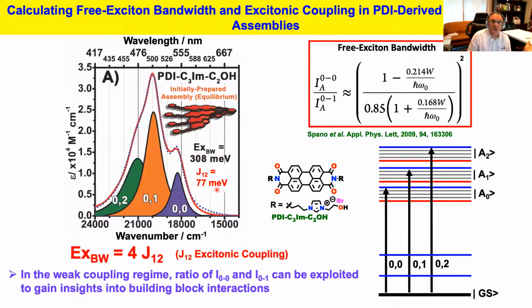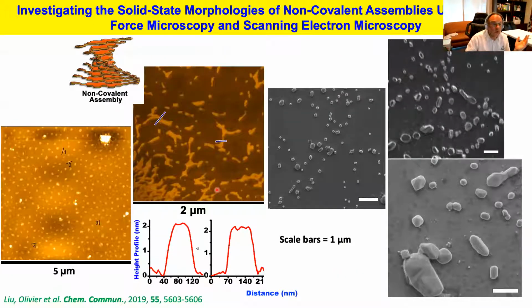Now, of course, I'm talking about solid state deposition. What is happening now if I take this sample and let's say I'm drop casting it or spin coating it? What's gonna happen is that you're gonna look at this. So essentially, if I'm looking at the nanoscale level using atomic force microscopy, I will see these islands of amorphous material, essentially with a height profile of 2 nanometers, and that essentially corresponds to the width of 1 repeating unit. But you do not really see hierarchical assemblies forming with this type of building blocks. Of course, we see similar features using scanning electron microscopy, where you can see these little dots forming, or at least at the length scale that we're accessing using SEM, it is very hard to talk about any structures.